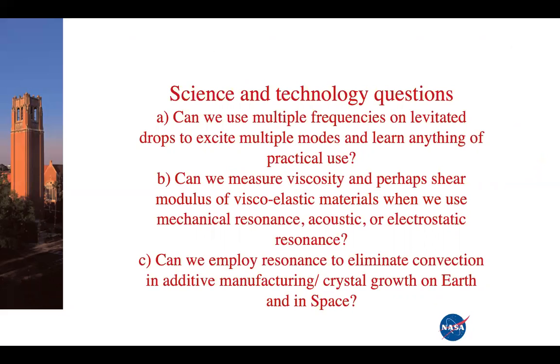Now, there are many science and technology questions that come out from the research that I've just talked about, and some of it have to do with this. Can we use multiple frequencies on levitated drops to excite multiple modes? And if we do so, can we learn anything and get anything practical out of this? Can we perhaps measure viscosity and even shear modulus of viscoelastic materials, not only when we use electrostatic resonance, but perhaps when we use mechanical resonance by, say, shaking a fluid mechanically, or by imposing acoustic resonance, by imposing acoustic signals. And this means that we can get more data, not just surface tension, viscosity, perhaps even shear modulus.